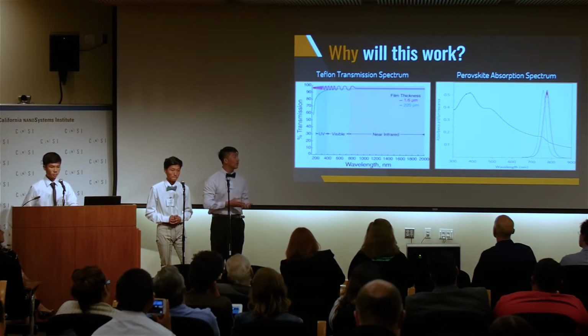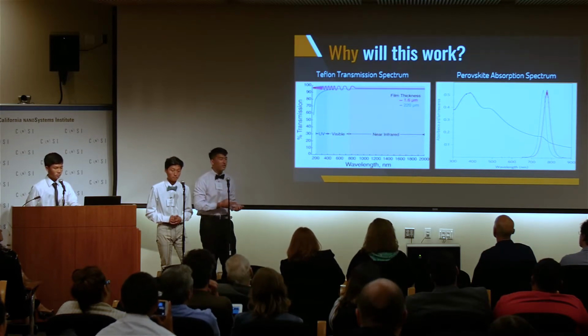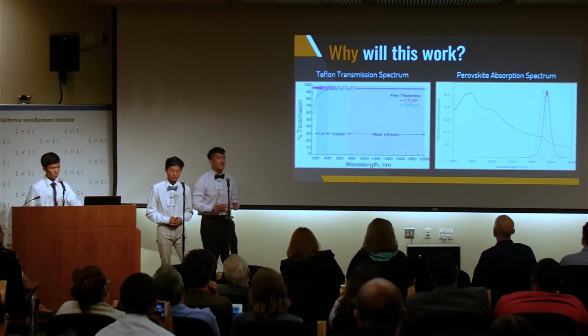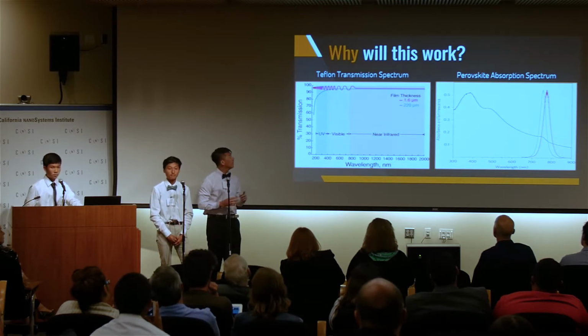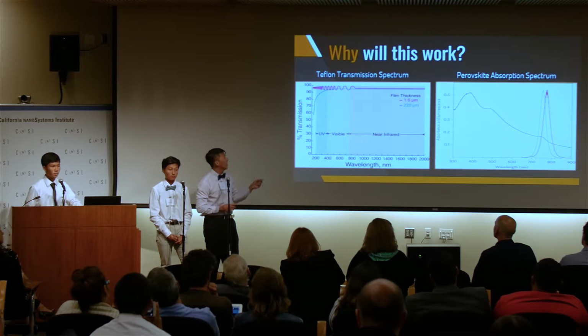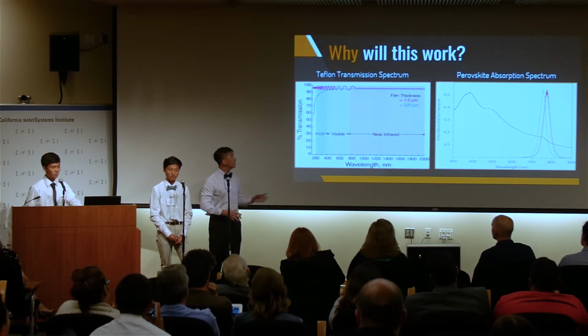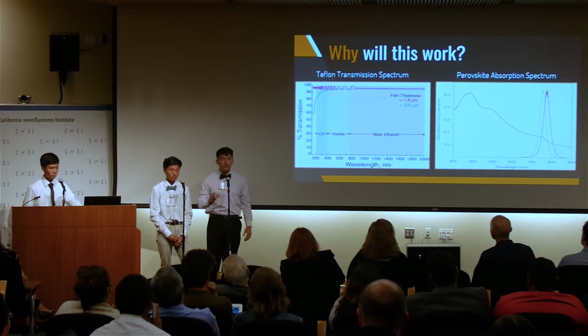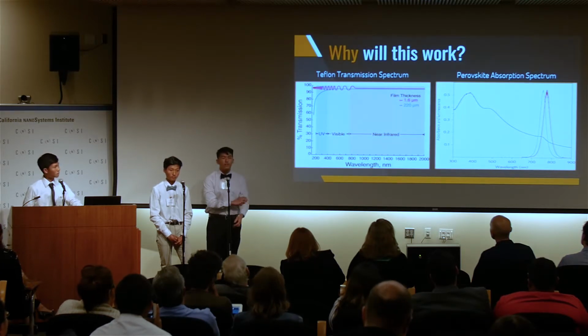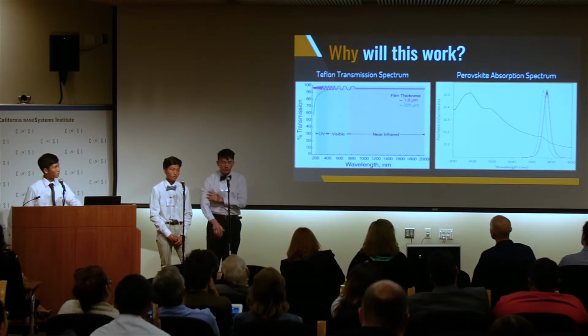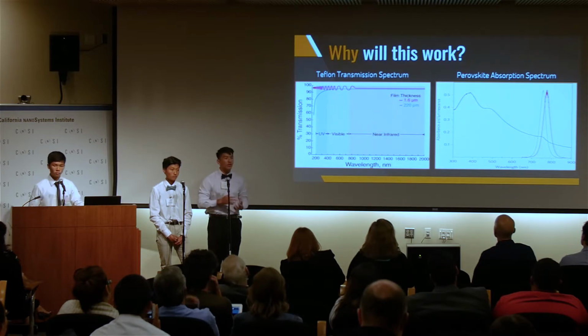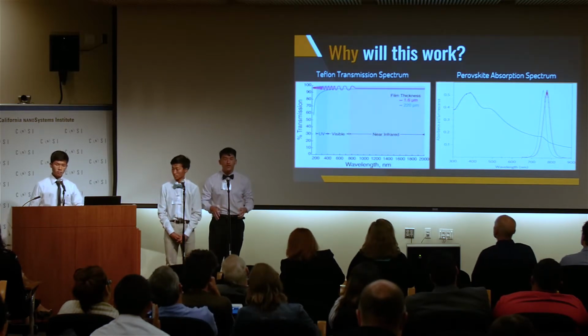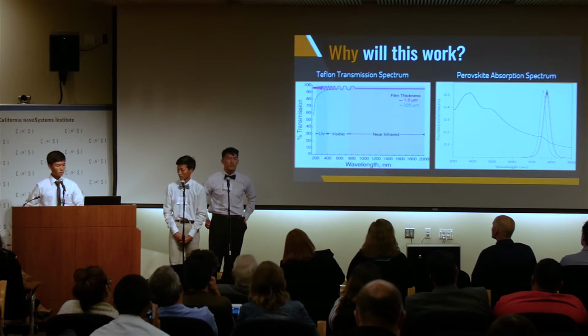In terms of solar cell, we had to look at their absorption and transmission spectrum for both perovskite and Teflon. And with Teflon on the left and perovskite on the right, from these 2 graphs, we conclude that Teflon has a 95% transmittance over most parts where perovskite absorbs. From this, we can conclude that Teflon will have little significance in affecting the efficiency of the perovskite solar cell.